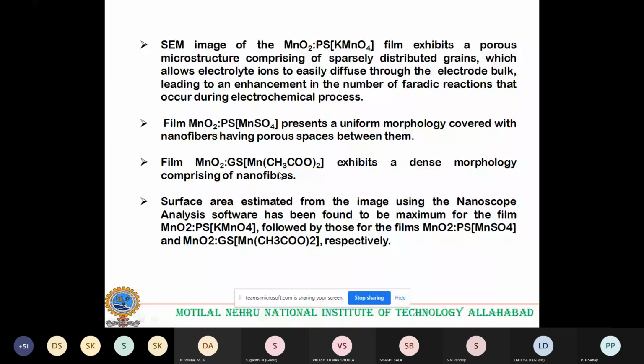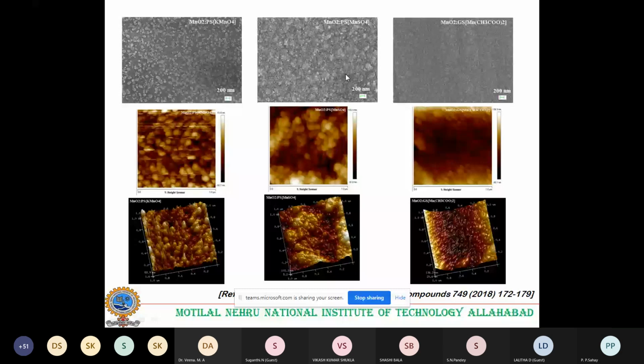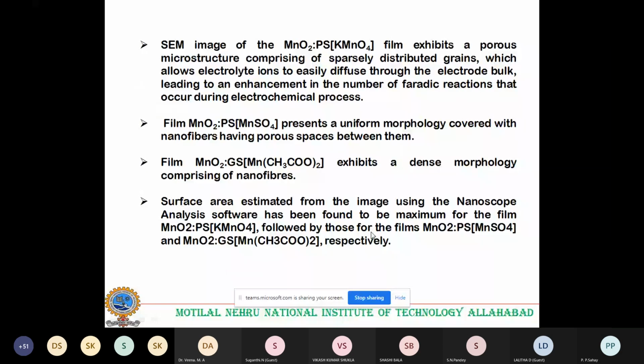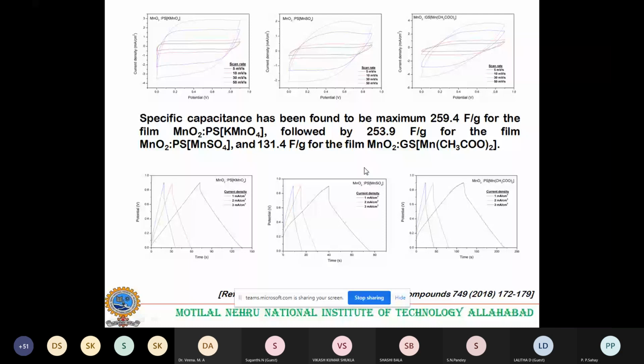The surface area estimated from the image, we calculated, that is the roughness. This is the figure associated with the cyclic voltammetry, and this is the galvanostatic charge figure. The specific capacitance has been found to be maximum, 259.4 for the potentiostatic mode in the case of KMnO4, followed by 253.9 for the film from manganese sulfate. So 259.4 in case of KMnO4, 253.9 in case of MnSO4, and 130 for the manganese acetate.